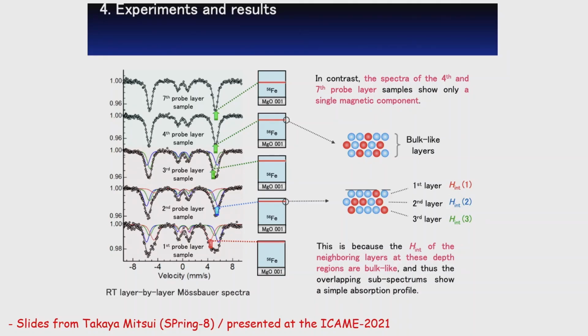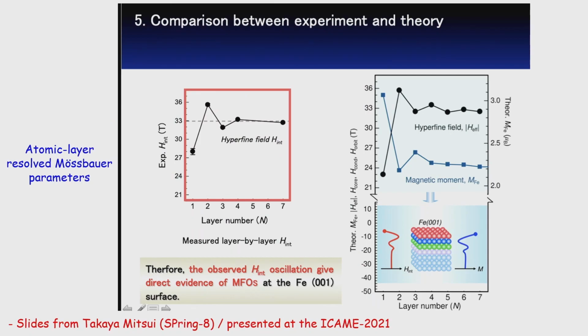You could see that at the interface you have a decrease of the hyperfine field. At the second layer you have an increase, and so on. And starting from the fourth layer below the surface, you have bulk-like properties. Then they are able to do atomic layer resolved Mossbauer parameters in the system. It was a very nice work.